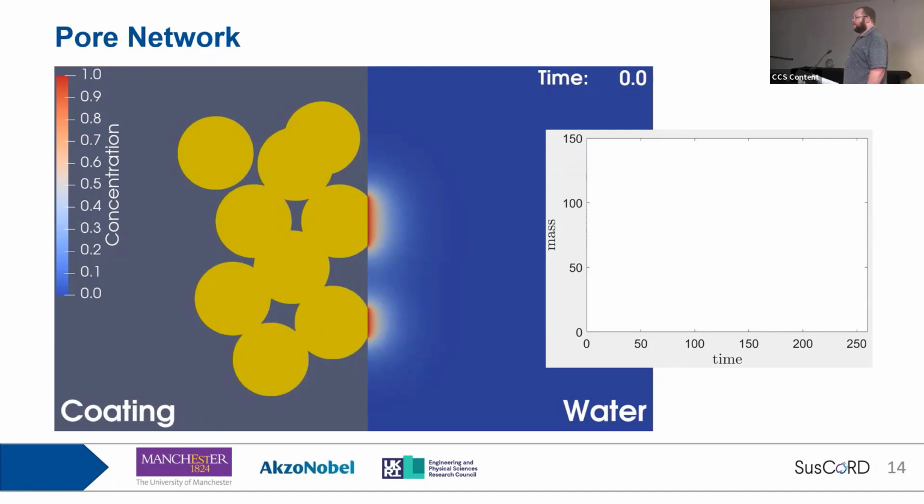So there's a similar problem in polymers where you swell something with a good solvent, called case 2 diffusion. And what happens there, you build a stress field. As the solvent comes in, the polymer swells and it builds a stress field, and that limits the rate of solvent going in. So in a similar way that you've done with your concentration, you have a limiting concentration profile. You could do a similar thing with the diffusion through polymers in case 2 diffusion. So it's a really nice idea, really nice bit of work. Thank you.